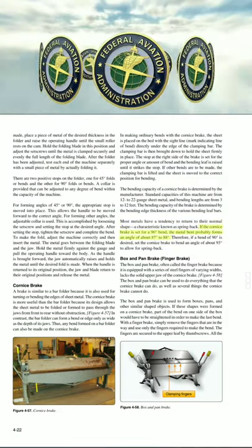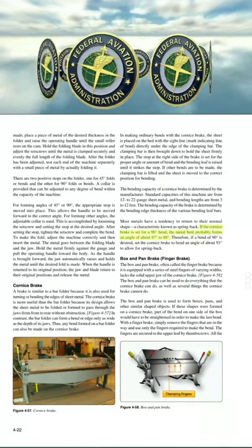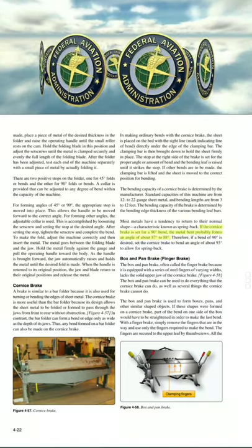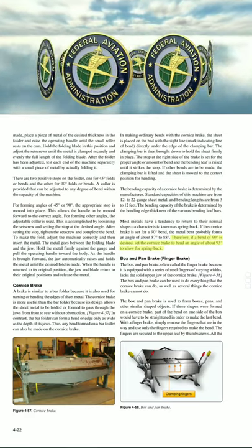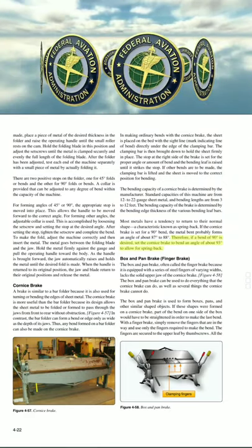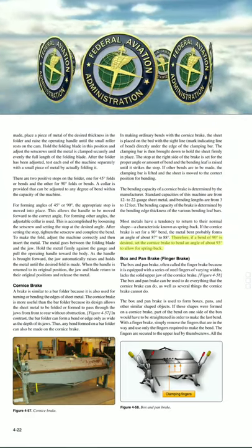If the cornice brake is set for a 90 degree bend, the metal bent probably forms an angle of about 87 degrees to 88 degrees. Therefore, if a bend of 90 degrees is desired, set the cornice brake to bend an angle of about 93 degrees to allow for spring back.